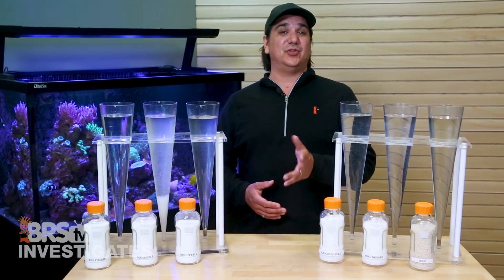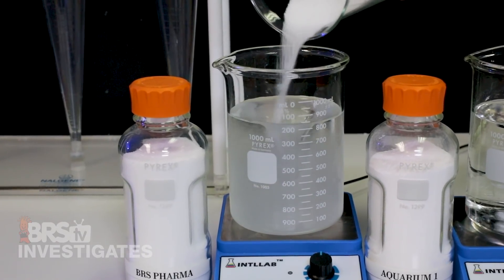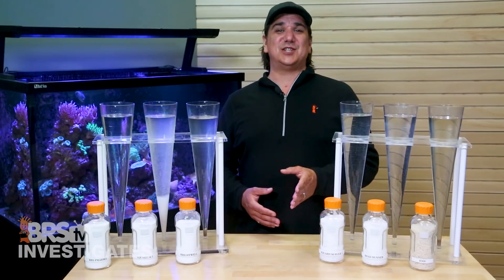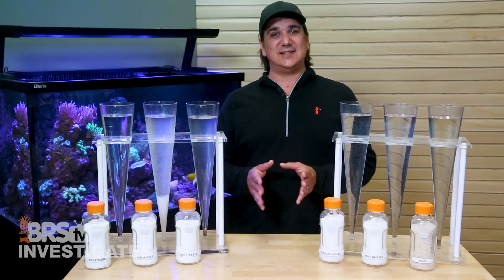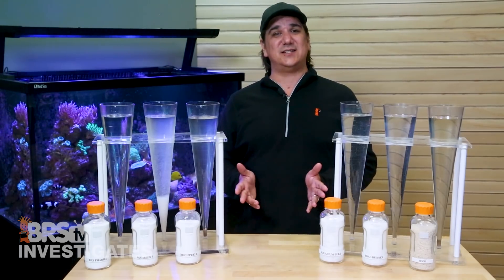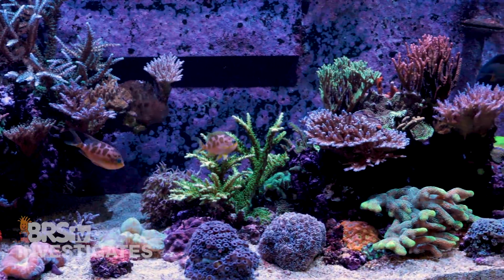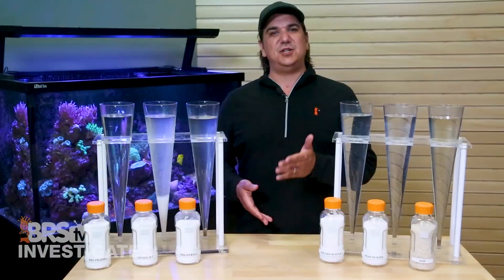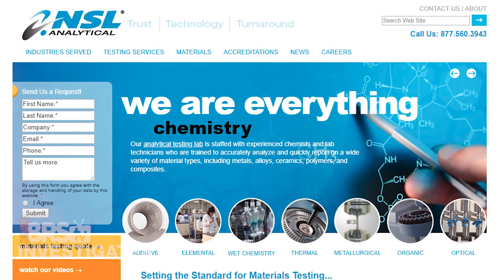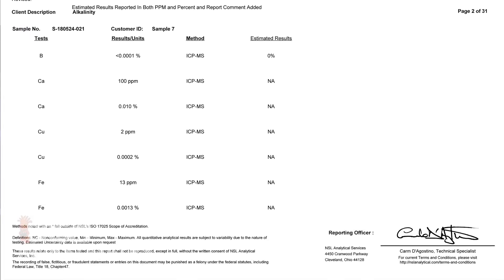Here is how we are going to test the materials. I collected the samples from our shelves, ordered a couple that we don't stock, and went to a big box hardware store for the ice melters. We will first take some visual assessments by mixing up 184 grams — close to a cup — of each in a liter of RODI water and then assessing total clarity, volume of water, and solubles. A visual assessment will only tell you so much, but if you can see it with the naked eye it is not a trace element. If it turns muddy brown, rusty red, or has a large amount of insoluble crud at the bottom, I don't really care what the ICP-MS testing says — I am personally not going to use it in my reef tank. Next we sent the six samples to NSL Analytical to be tested with ICP-MS and other methods for 21 parameters: 16 individual parameters and a group of heavy metals reported together. This type of testing should provide a solid window into the suitability for a reefing application.